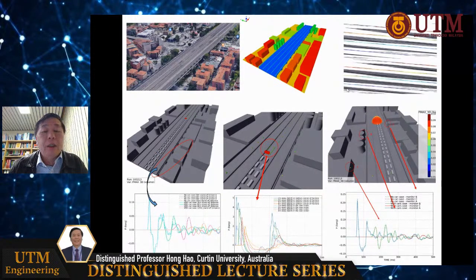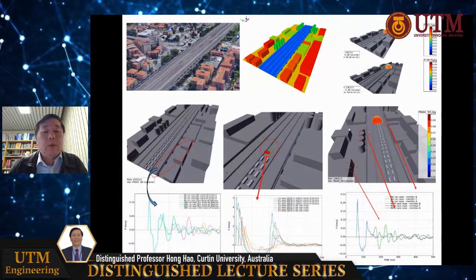It's a BLEVE explosion. We did a simulation. We tried to replicate this BLEVE explosion. And you see that very close to the explosion center, we predicted, estimated the blast pressure is about 5 bar. That means about 500 kPa. That is why it caused a collapse.